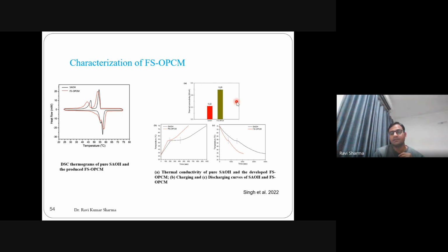Thermal conductivity was a very interesting result. Graphitic carbon nitride, as you know, is a simple carbon material, but it's a white carbon material with higher thermal conductivity. Once added into the PCM, the thermal conductivity was enhanced, almost doubled, from 0.22 to 0.49. When it is doubled, it takes lesser time to complete one melting and freezing cycle. Follow the black line for pure PCM and the red line for composite PCM, FSPCM. The composite PCM takes lesser time for one complete melt-freeze cycle.